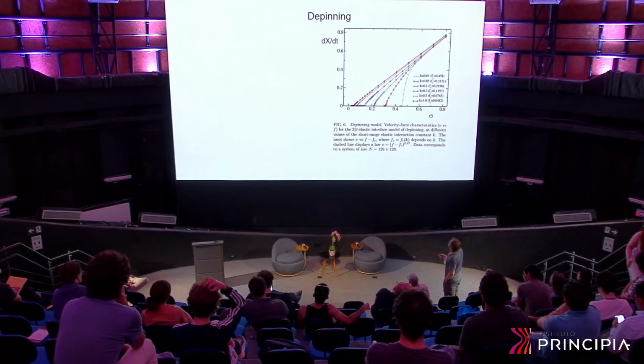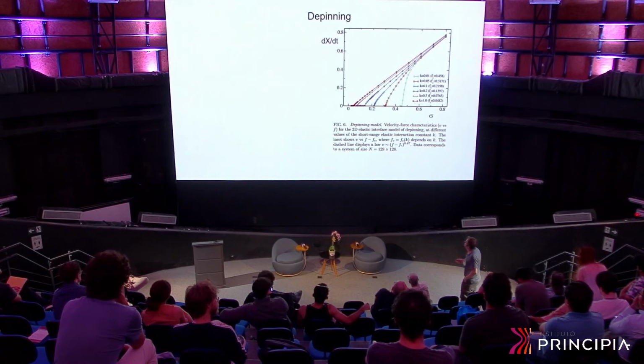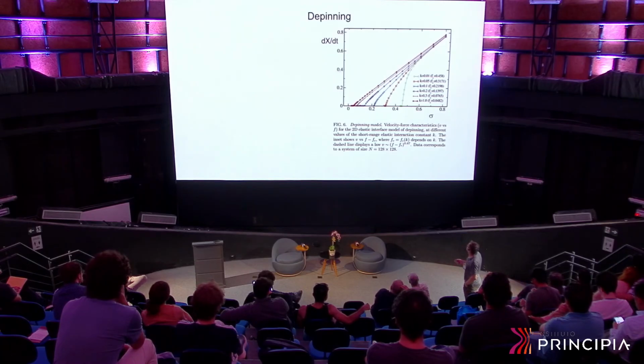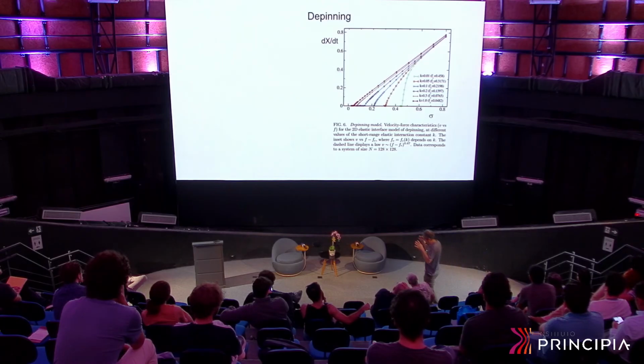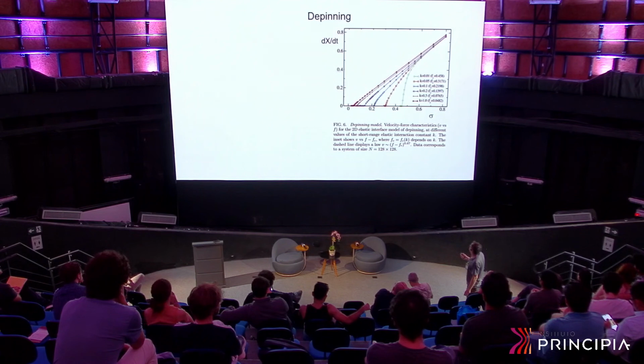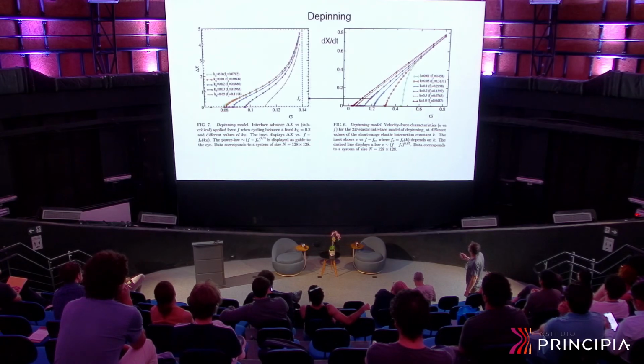So what remains is just to show the results of numerical simulations, and the interpretation is just the one that I have given already. For instance, for depinning, we have here the flow curves obtained at different values of the spring constant, but these are the standard curves when the spring constant is constant over time. And in fact, you see that there is a critical value of stress, and from here the system deforms.